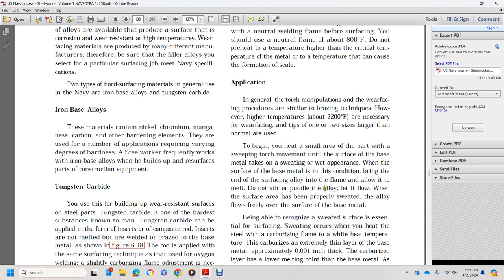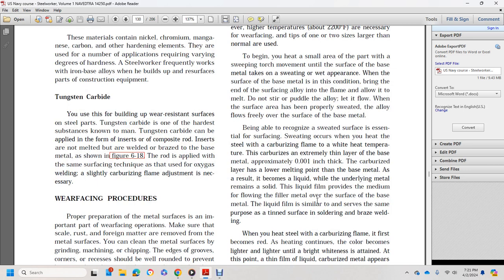Do not stir the puddle of the alloy; let it flow. When the surface has been properly sweated, the alloy flows freely over the surface of the base metal. Being able to recognize sweated surfaces is essential for surfacing. Sweating occurs when you heat the steel with a carburizing flame, which carburizes an extremely thin layer of the base metal, approximately 1/1000 of an inch thick. Carburized metal has a lower melting point than the base metal. As a result, it becomes liquid while the underlying metal remains solid.